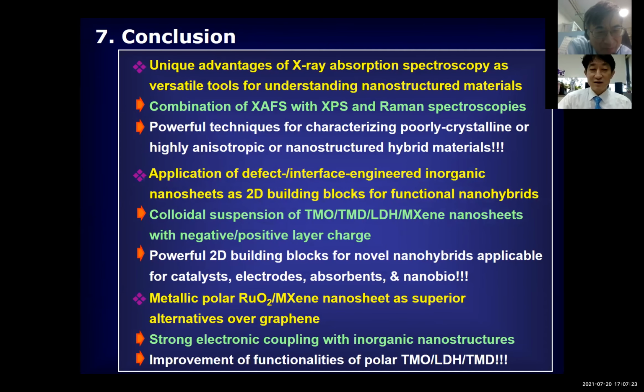We widely apply the X-ray absorption spectroscopy, especially in combination with XPS and Raman. In this way, we can easily characterize poorly crystalline materials, highly anisotropic materials and nanostructured hybrid materials. In terms of synthetic research, we applied the 2D inorganic nanosheet as a building block. We focused more on the engineering of defect structure and the interfacial structure.